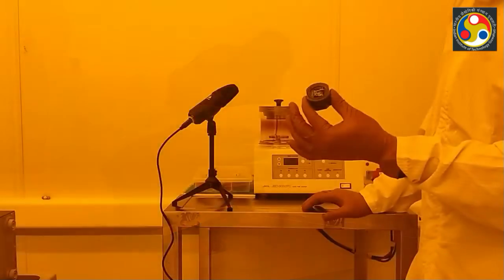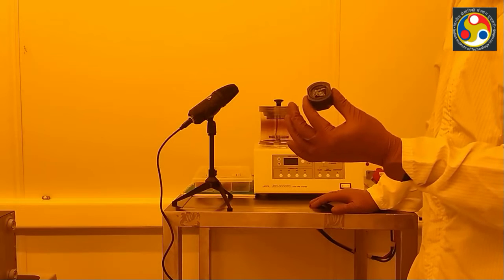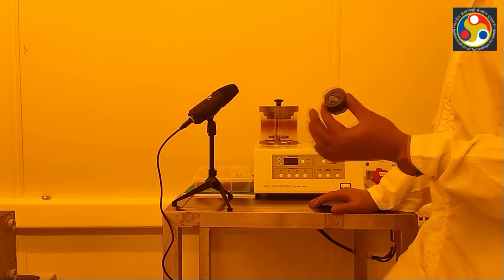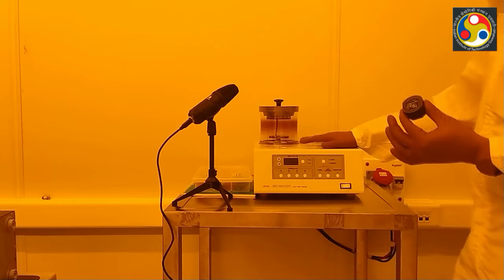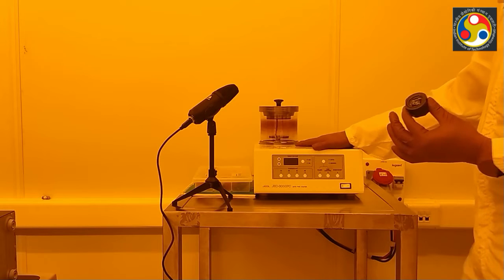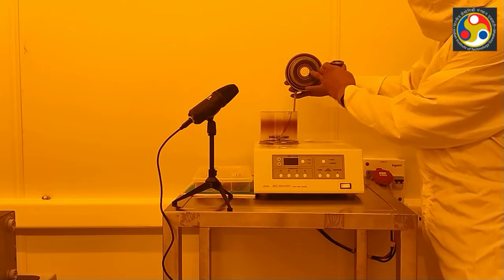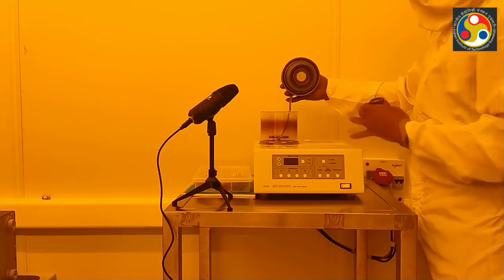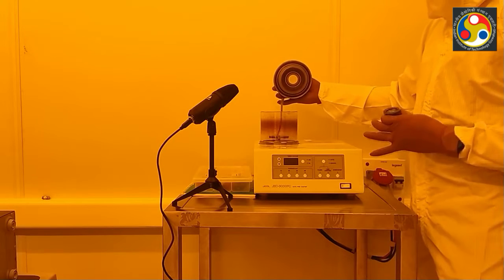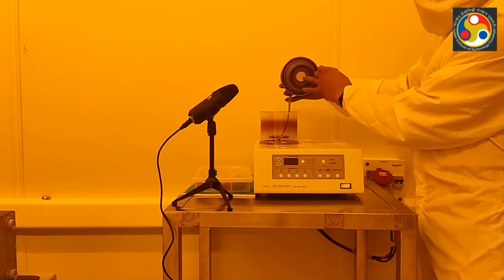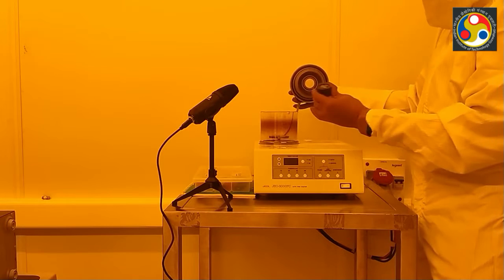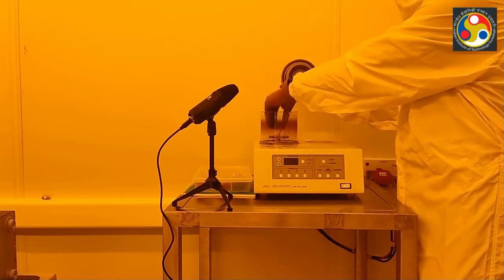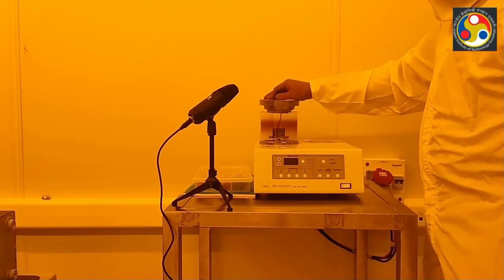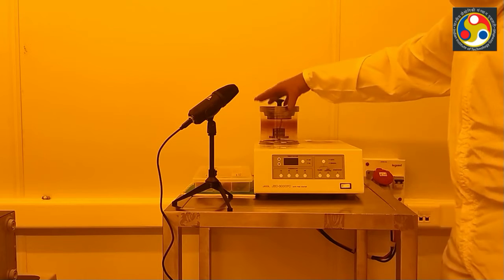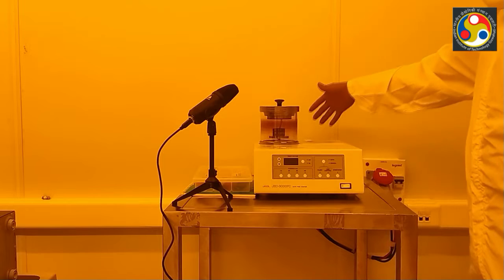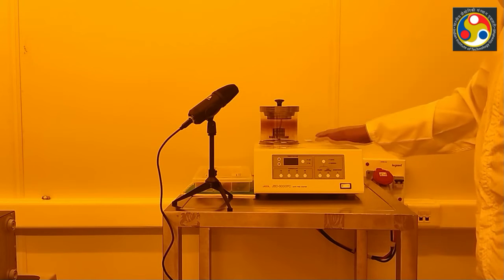Let's see that coating. In this system we use platinum metal coating, and this is the platinum coating system. This is a sputter coating system with a platinum target. This is the platinum target here, the target material. About sputtering I will make another video. We will keep the sample holder inside this vacuum chamber. This is a vacuum chamber in this system. We will keep it inside, and there is a vacuum pump connected to this sputter coater.